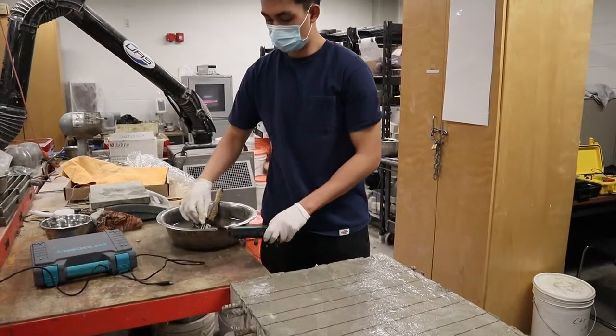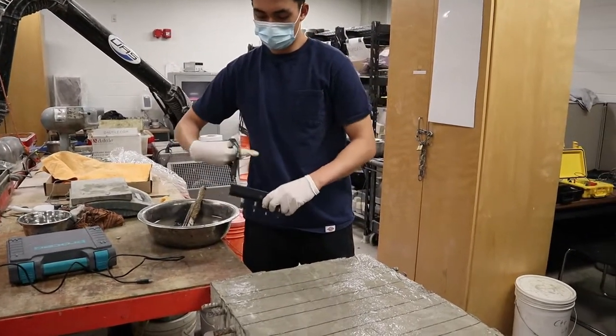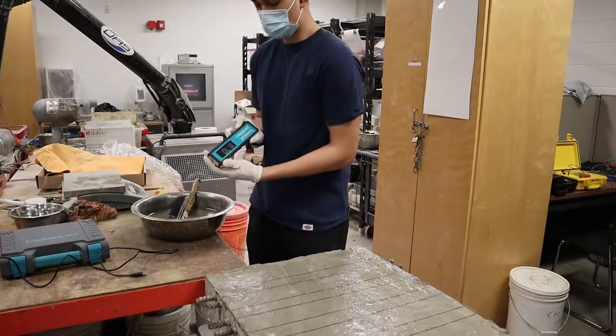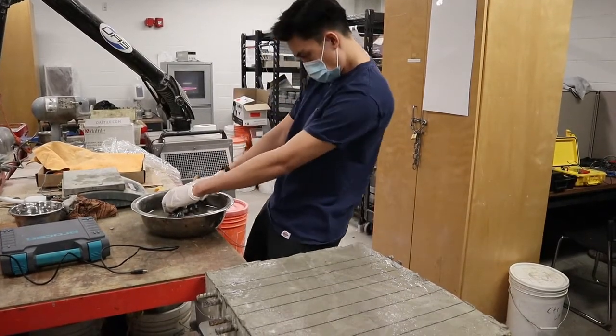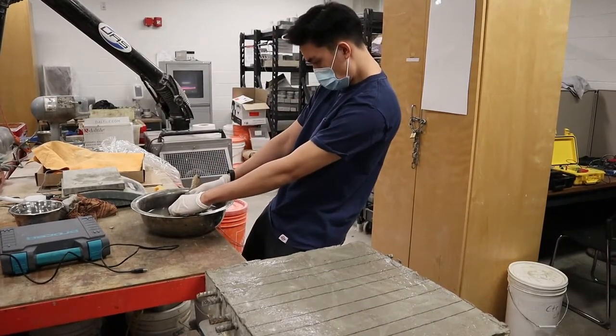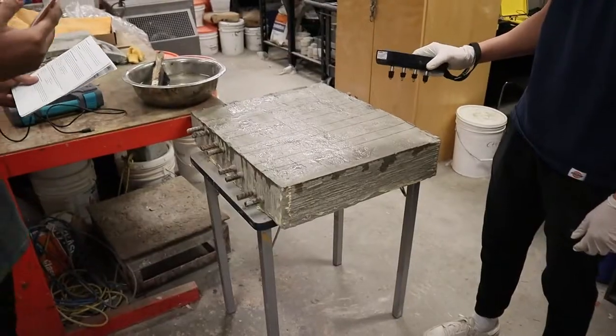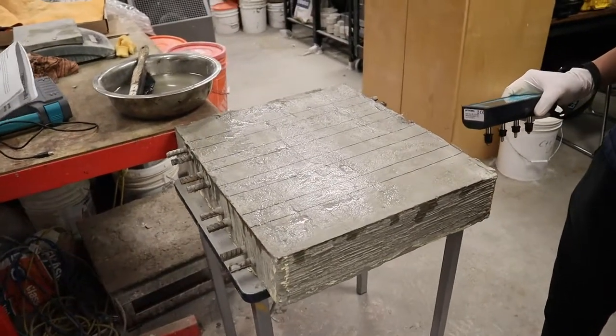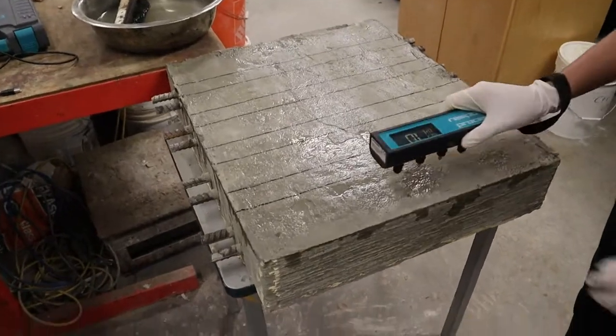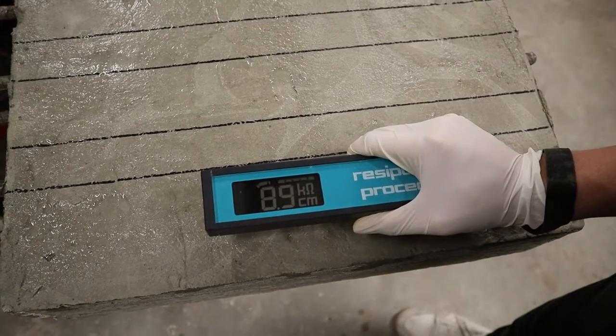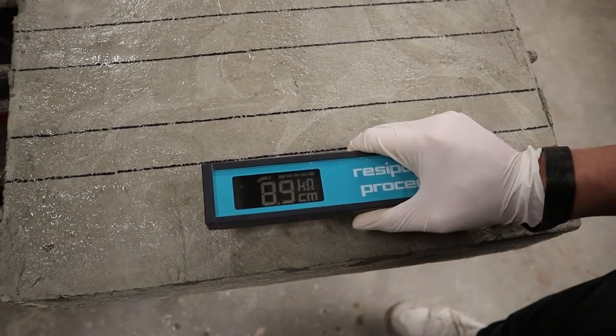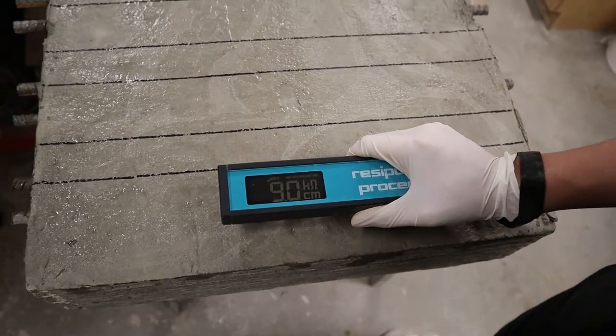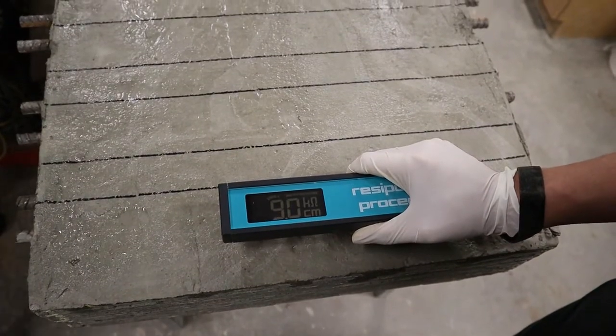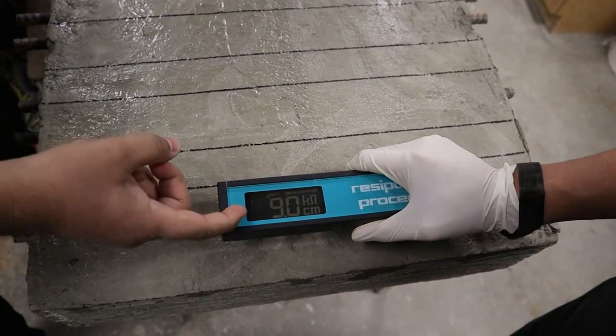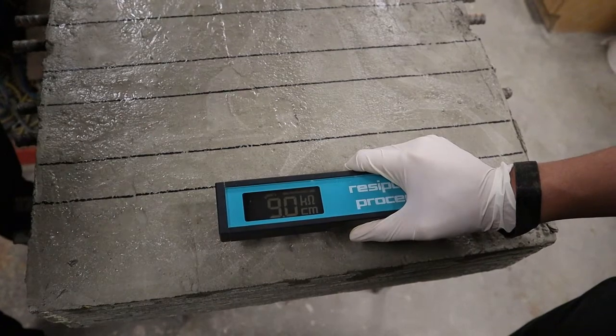Now we will be using the ResiPod, and it will be dipped in water several times to ensure that the surface of the sensors is very wet. The ResiPod will be placed down on the surface until the outer two rubber caps rest on the surface. The test will be conducted 5 times, one between each row of the bars, and the results will be recorded. For instance, right now the value is 9.0 kilo ohm centimeter.